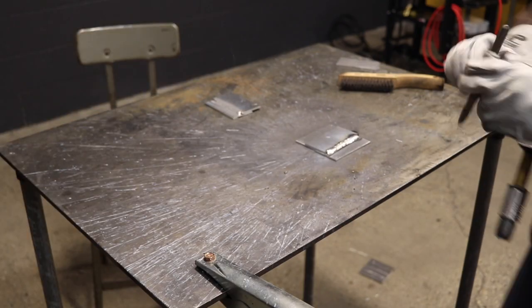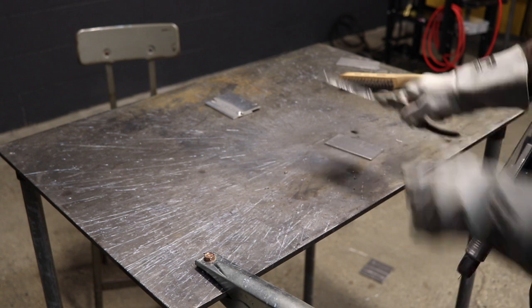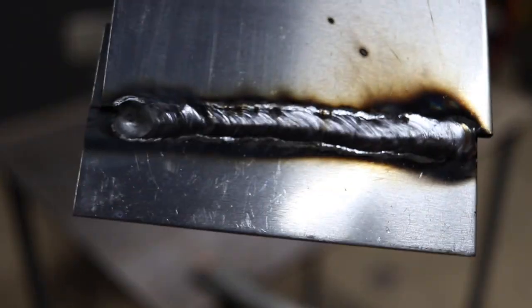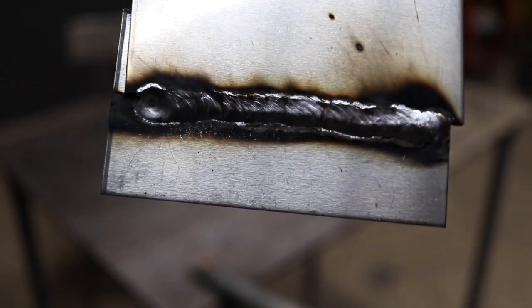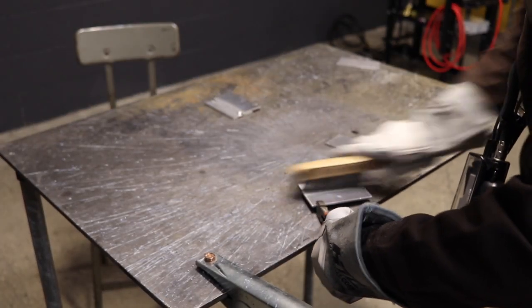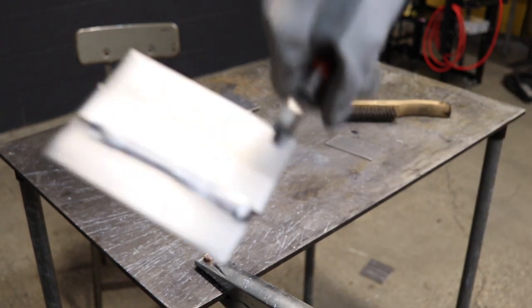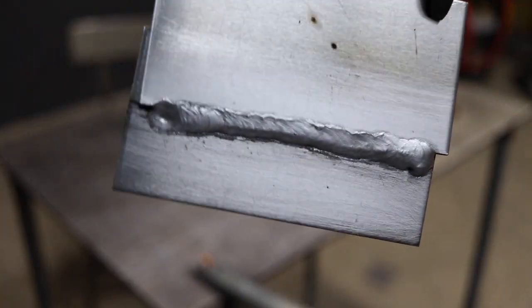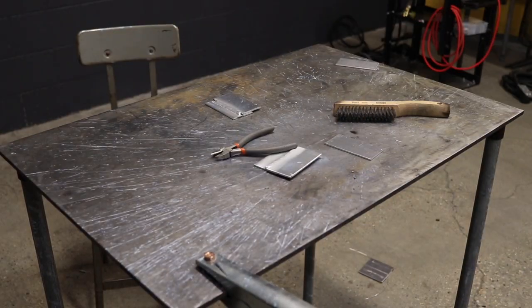Here you can see there's a lot of popping and crackling going on due to the voltage being set too low for the material thickness that we are welding. The travel speed on this weld is good, it's a little slow. You can see that on the resulting weld there is some undercut at the top. And the goal is to obtain a spray arc using the spool gun. In order to do so, you need enough heat to penetrate the oxide layer, but you have to move fast so you don't burn through the material itself, since aluminum is a heat conductor.